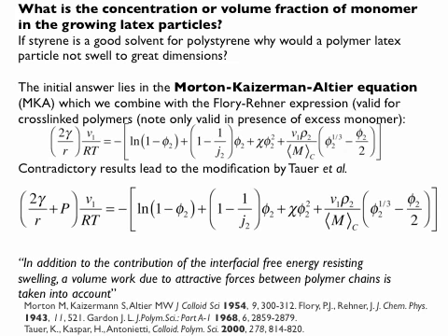But if I now swell, I move these groups further apart from each other. So you could argue that interfacial tension in this case is not a constant, but is a function of the swelling of the droplet as well. Which means you have to make it more complex by writing interfacial tension as a function of the radius of the particle.